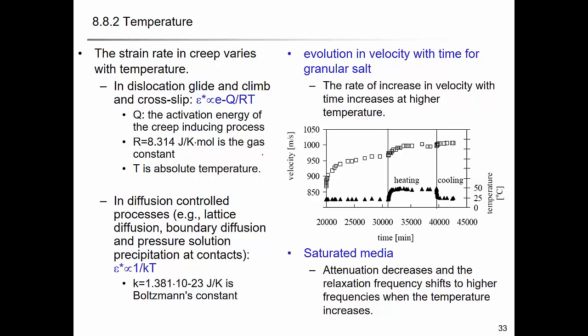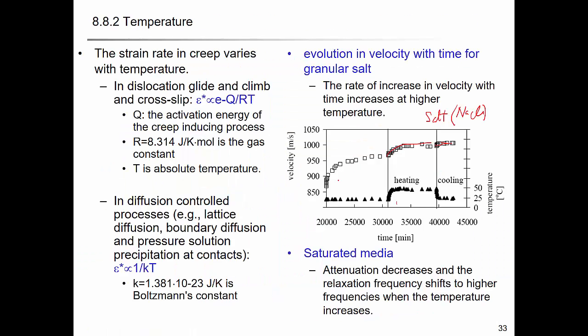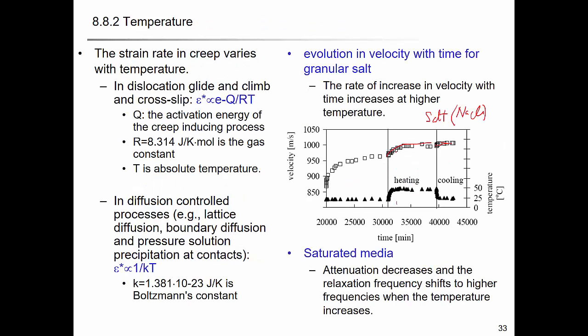The last effect is the temperature effect. As you increase the temperature, you also increase the vertical strain and accelerate the creep behavior. For example, here they use just table salt, so sodium chloride. And when they heat it to 50 degrees Celsius, you have increasing velocity. And during cooling, it stays the same. So this is the temperature dependent creep behavior.